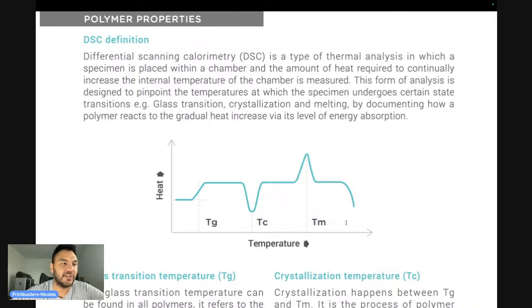And then TM is the melting temperature. TM is the temperature that is high enough to break the crystal. So if the melting temperature is the temperature at which it breaks the crystal, now you realize that an amorphous polymer, not a semicrystalline, that doesn't have any crystals, doesn't have any melting temperature, right? Because it's defined as breaking the crystal. If there is no crystal, then there is no melting temperature. It's basically at TG. At TG, it will become soft. You break all the secondary bonds, and then it will just become more and more malleable, right?